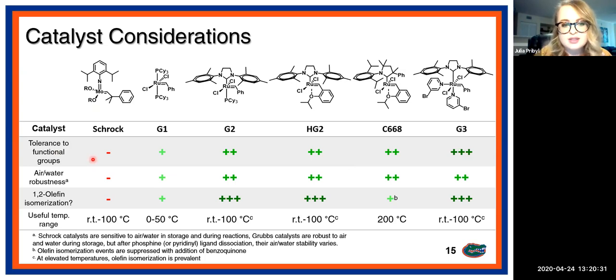A little bit later on, the Grubbs first generation catalyst, which is this structure here with the 2 phosphine ligands, has really become the darling of ADMET polymerization because it has pretty good tolerance to functional groups. And it also has a relatively low incidence of 1,2 olefin isomerization. So it's pretty easy to handle and it produces very precise polymers under ADMET polymerization conditions.